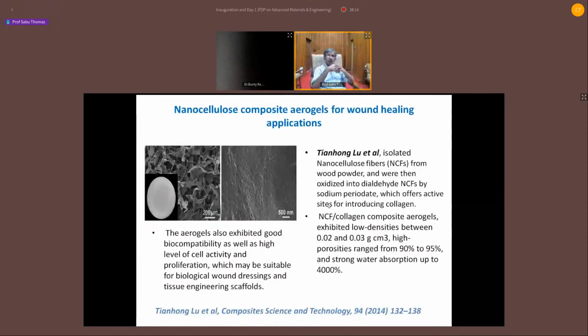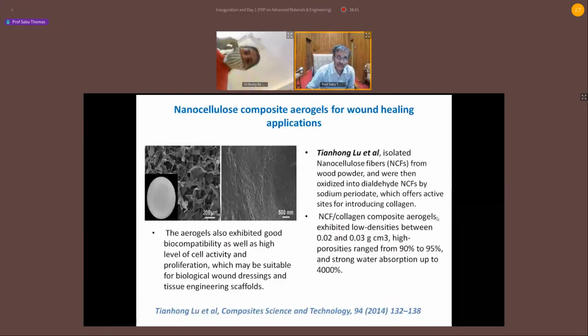Lu and co-workers from China, there is some interesting one. Combined nanocellulose with collagen. They made a hybrid configuration, nanocellulose and collagen, and they made composite aerogels. And when they combine nanocellulose with collagen, it became more compatible, highly biocompatible. And look at the density, 0.02 to 0.03 gram per centimeter cube. And porosity is 90% to 95%. Water absorption went up to 4,000. They made a fantastic lightweight material. And Professor Lu and group suggested that this is a fantastic material for wound dressing and tissue engineering stuff.